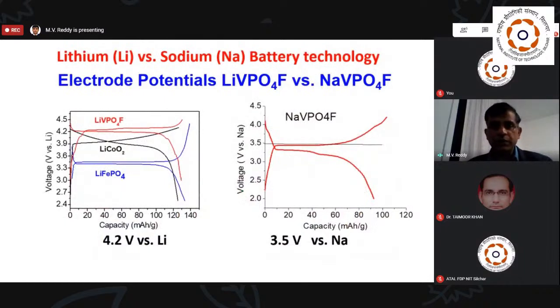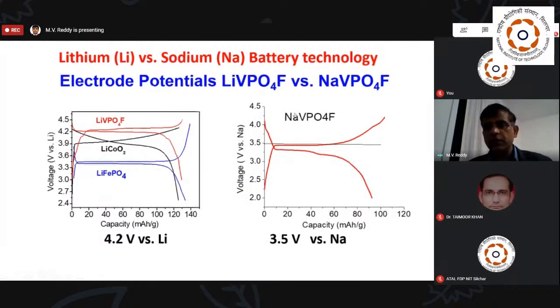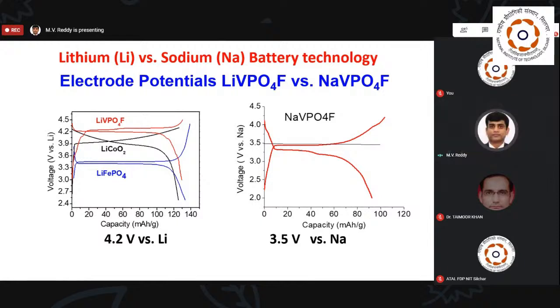One simple example is the vanadium-containing compound with almost the same structure, sodium versus lithium. Here with lithium you get nearly 4.2 volts, with sodium you get nearly 3.5. That's why the voltage and energy density come down automatically. But for stationary applications, for example the grid, a slightly bulkier, lower-voltage cell is no problem. So depending on the application, these are alternative approaches people are pursuing.